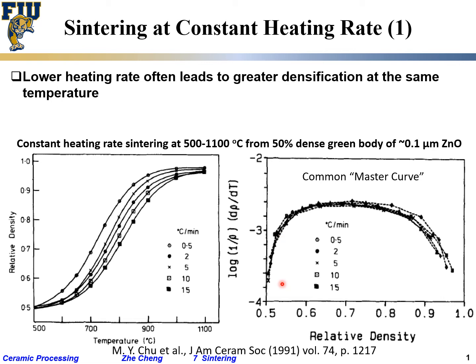Initially the densification rate is slow. Towards the end it is also lower. But in between — roughly from 0.55 to 0.85 relative density — it is more or less constant and follows the same line regardless of whether your heating rate is slow or fast. When we perform this normalization across different heating rates, the so-called temperature-derivative densification strain follows the same trend.